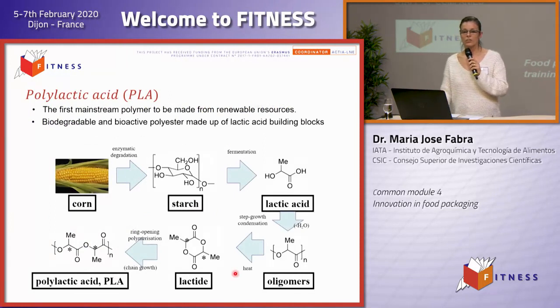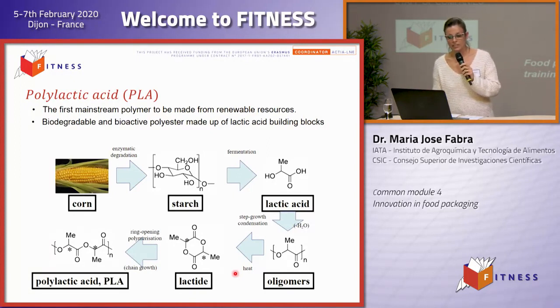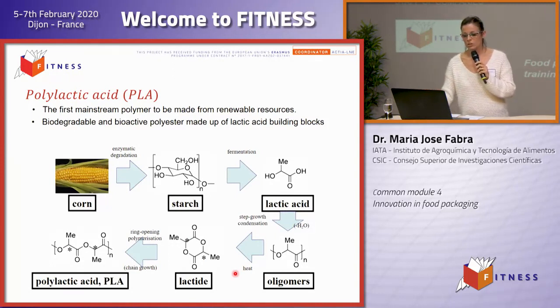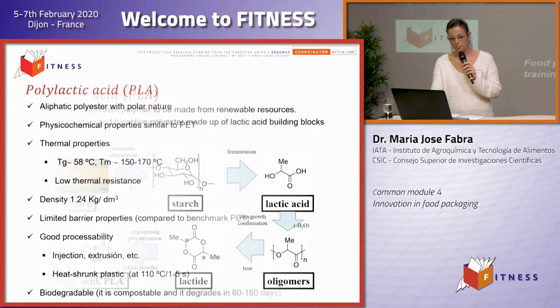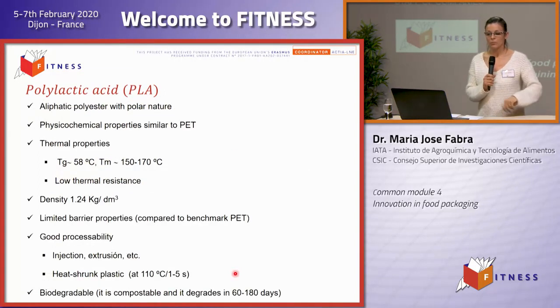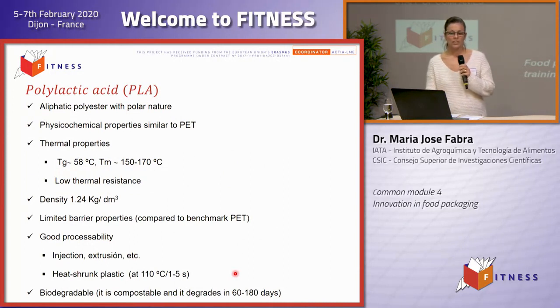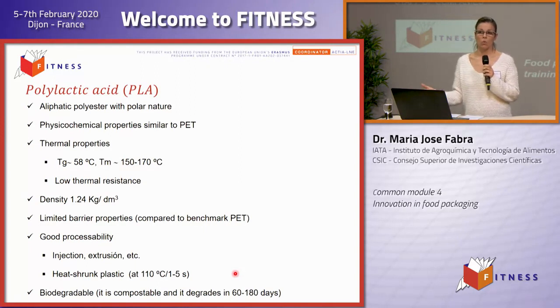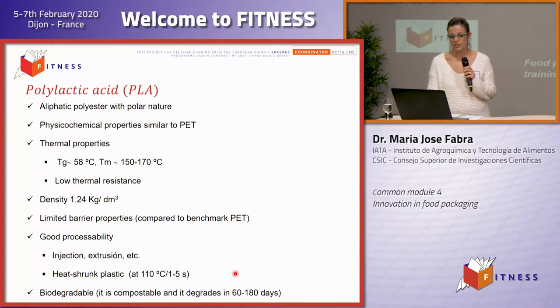Polylactic acid is another interesting biodegradable material which can be obtained from corn. After a fermentation of starch, we can obtain lactic acid, and from this lactic acid we can obtain oligomers, and by polycondensation, we obtain the PLA. PLA is an aliphatic polyester with polar character, whose physicochemical properties are similar to PET, which is one of the most common petro-based materials.